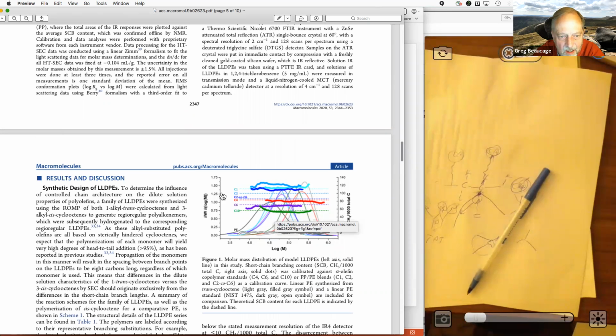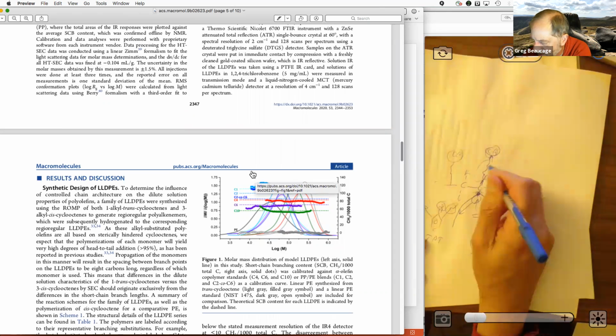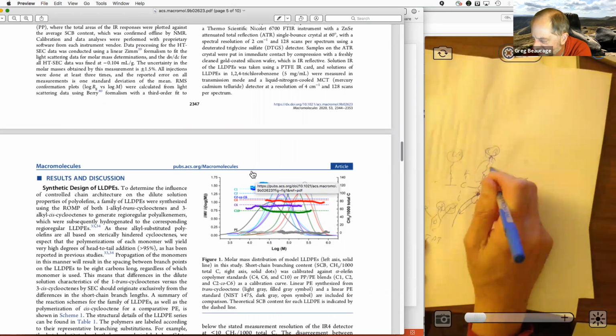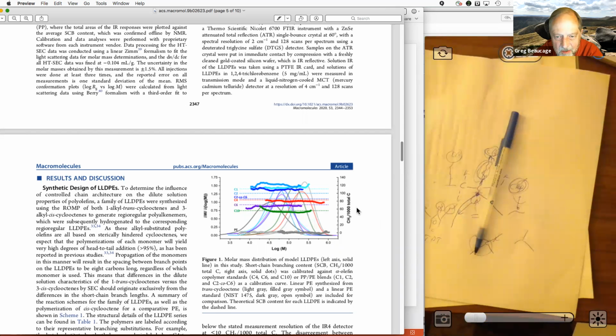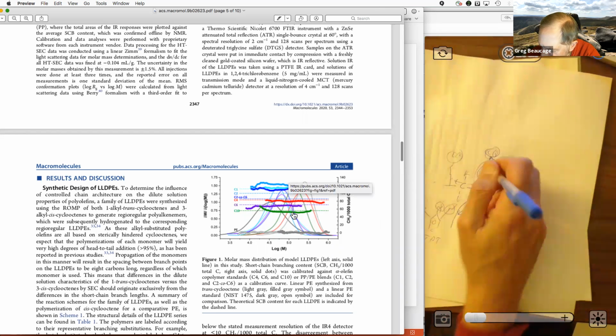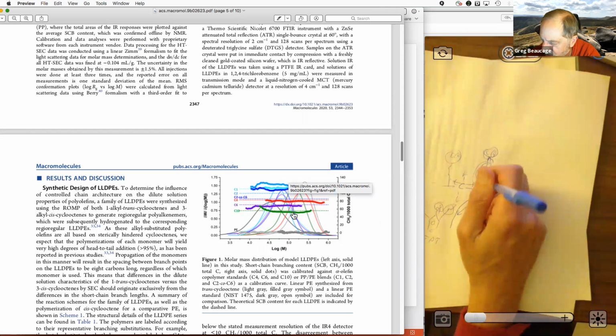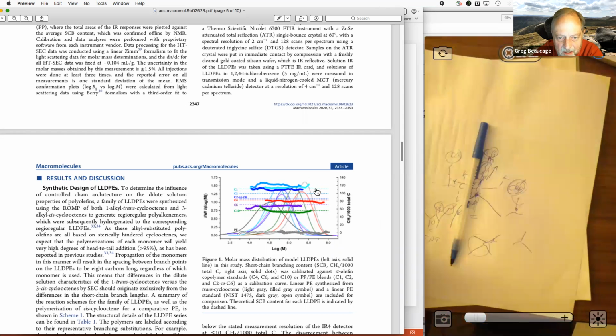Right, so in the C1, so the branches, adding the branches dilutes the methyl groups. There's a branch in every 8, but there's going to be dilution of the CH3 by the branch itself. When it's 10 long, it's going to dilute out the branches. So the 10 has the lowest CH3 per 1,000 carbon, because you're including the branch carbons too. Right. So in fact, since it's 8 between and then 10 up here, that's going to be something like 50% less than the CH3 of the C1. Right, so the C1 is something like 110, and 50% of that will be 55, and then the C10 is about 55. Right, so it works pretty analytically to count the number of branches.